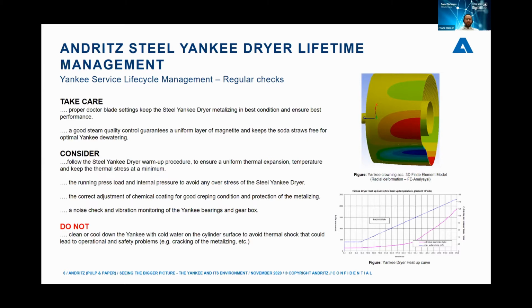Inside the Yankees, steam quality plays a major role. A good steam quality control guarantees a uniform buildup layer of magnetite. This is the black oxide. This keeps the siphon straws free, as we have no particles removing. As soon as we discover any red oxide or corrosion products inside the Yankee, this probably clogs the siphon straws.